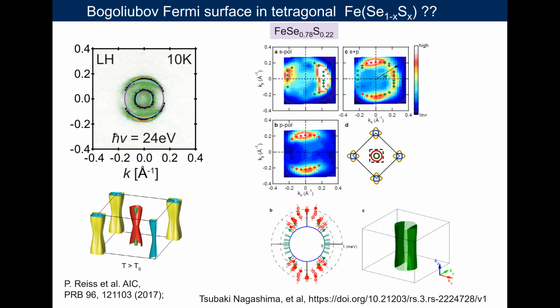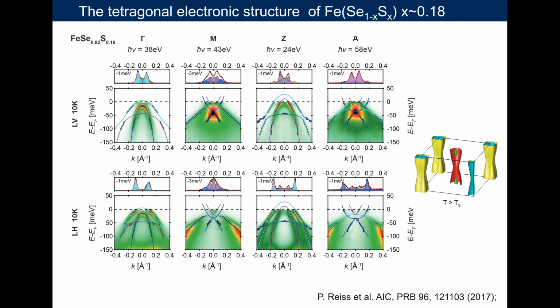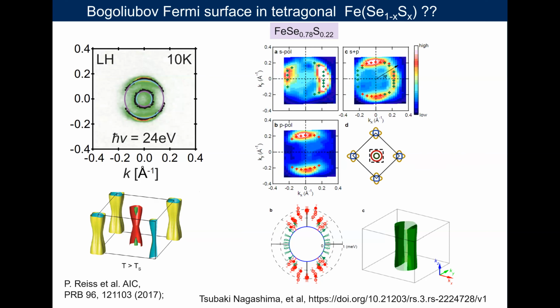I think these spectra are taken using different light polarization. As I mentioned, using different polarizations, linear vertical and linear horizontal, you see different bands, different dispersions. And here it is the same: using S and P polarization is equivalent to that. That means when you see this, you are mainly sensitive to this pocket, very likely because of a particular orbital character, whereas in the other polarization you are sensitive to the other pocket. But then they measure the gap of these pockets, and they suggest that there is a very anisotropic gap in a system which is tetragonal.